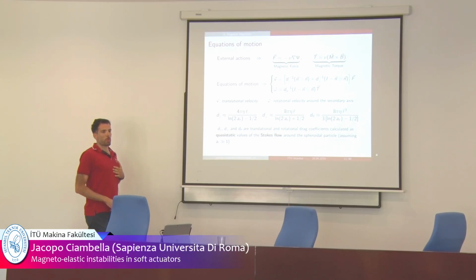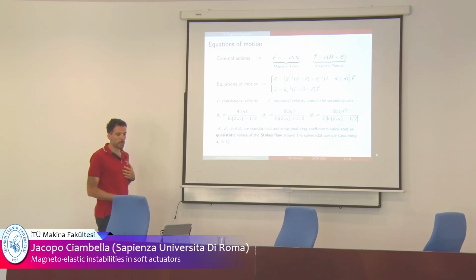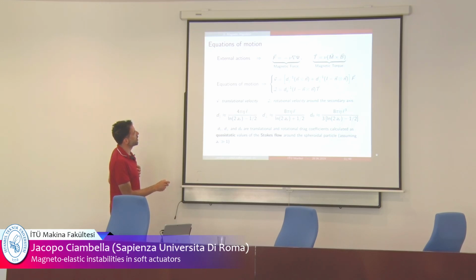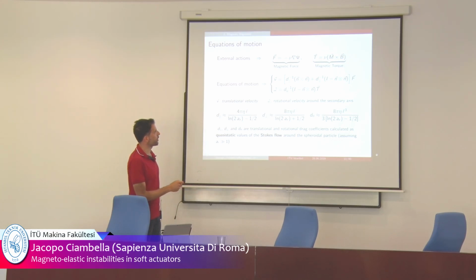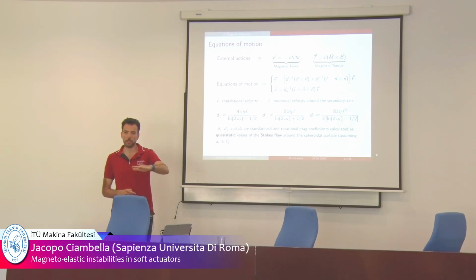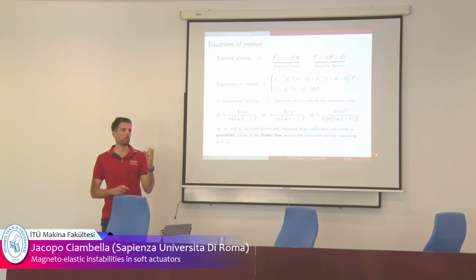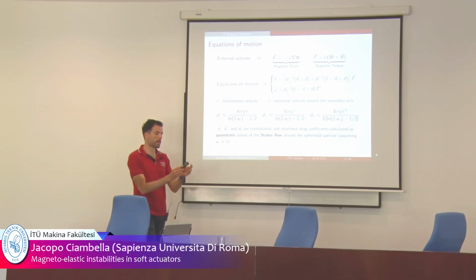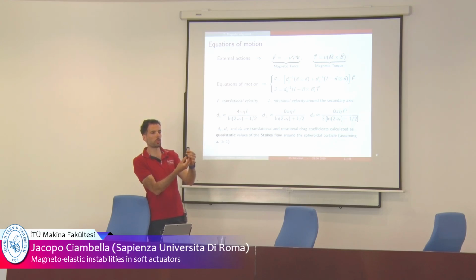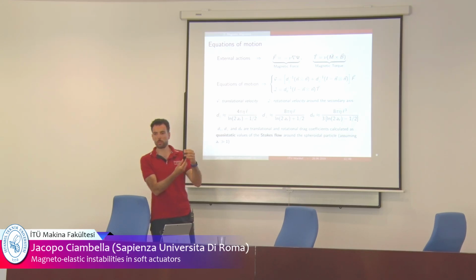Let's write some equations of motion. Very simple. We have the magnetic force, which is the gradient of the magnetic potential I showed you before, and the magnetic torque, which depends on the cross product between n and B. Nu here is the volume of the particle. Once you have the force and the torque, you can write down the equation of motion. V is the translational velocity of the particle. Omega is the rotational velocity along the secondary axis. What it means, secondary axis, is that we are not taking into account rotation around the main axis of the particle. We are not interested in those.